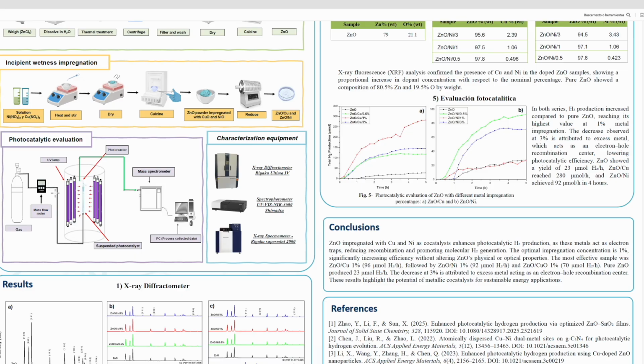It's important for the reaction to be maintained in an inert atmosphere, since we don't want reactions or for our molecules to recombine with oxygen, forming water again or generating species we're not interested in. Well, once photocatalysis occurs, the hydrogen produced is sent to a mass spectrometer in order to quantify how much hydrogen we're generating and then process the data.